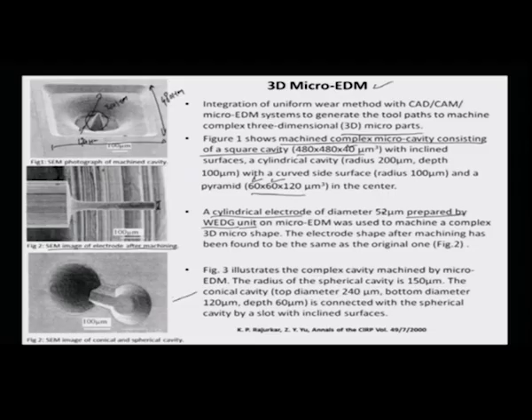Figure 3 here illustrates a complex cavity machined by, again, a micro EDM tool. The radius of the spherical cavity in this particular region is about 150 micrometer, and the conical cavity has a top diameter of 240 microns and a bottom diameter of 120 microns, with a depth of about 60 microns, and this conical cavity further is connected with this spherical cavity.